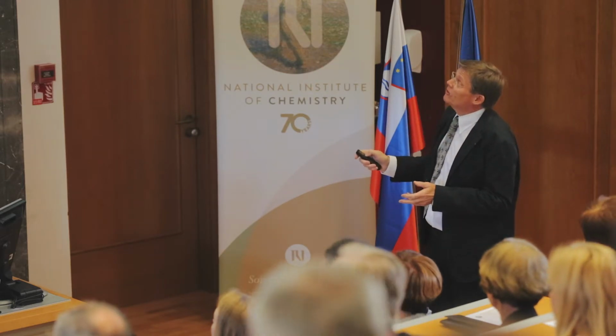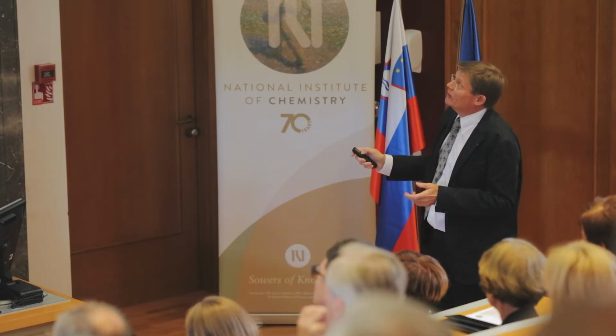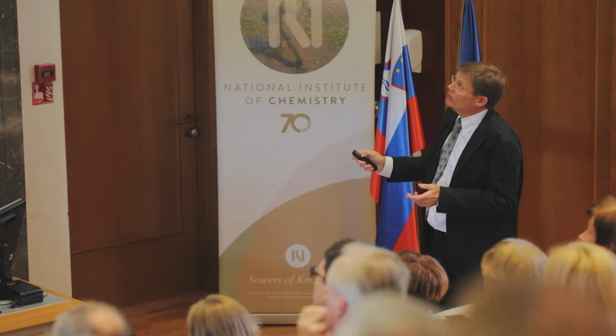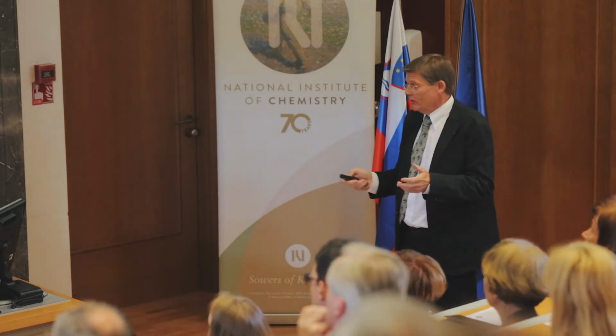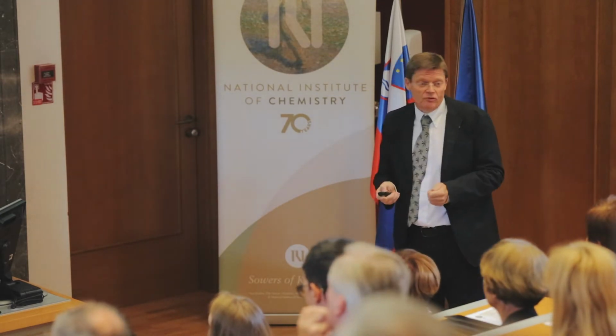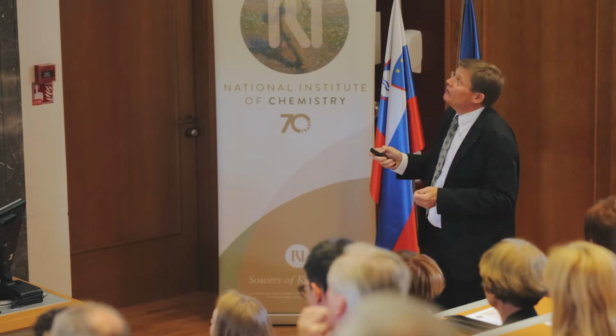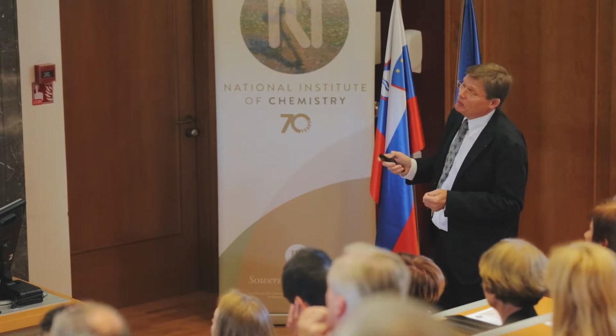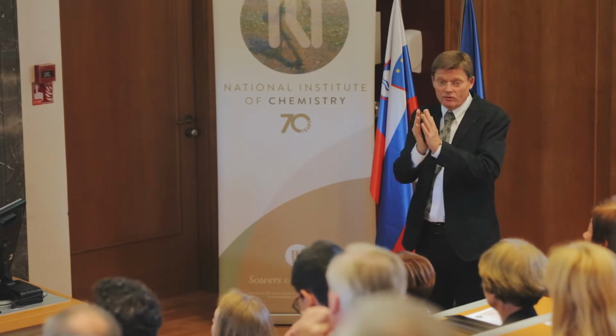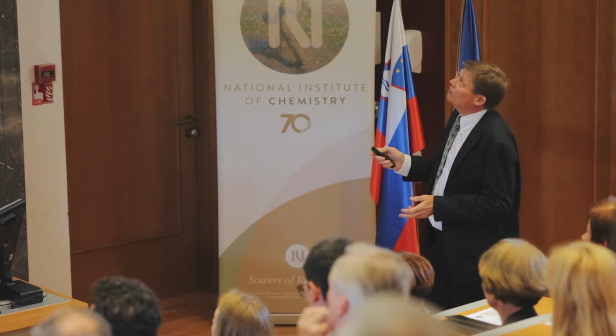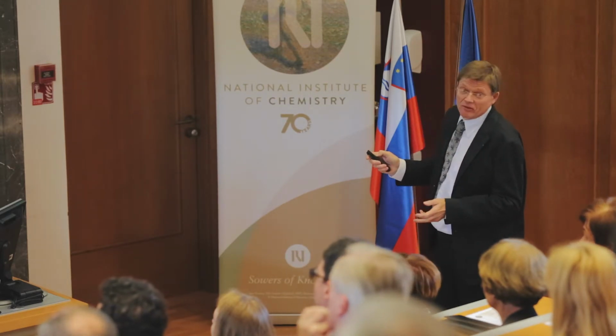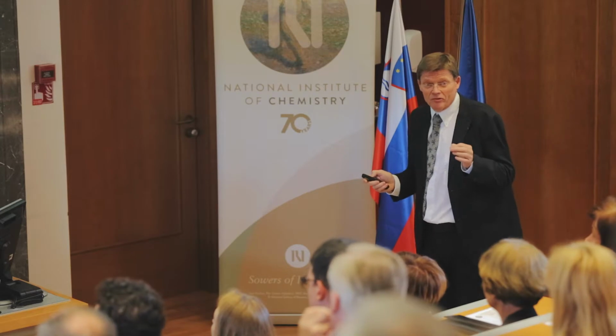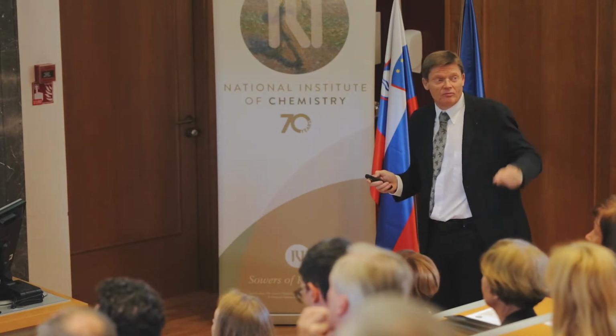Now, the capacitors here, fortunately, are very different. The dielectric capacitor is very small. The typical measure is like picofarads. These interfacial ones are maybe microfarad because the interfaces are thin. And even much larger is the chemical capacitance. It's a very, very large capacitance, maybe millifarad, orders of magnitude larger.